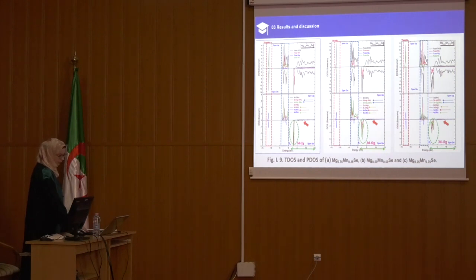The first one, from 1.2 to 5 electron volt, is formed by 3d T2g manganese states for the spin down case, where the second part, between 5 and 15, is mainly composed of a mixture of 4s, 4p Se states.